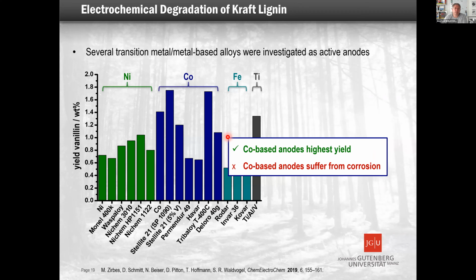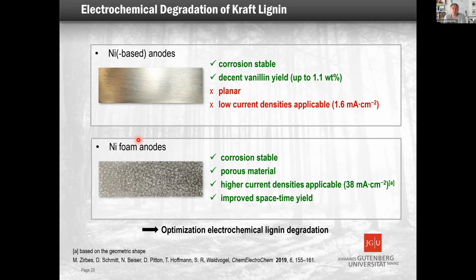It turned out if you have different metal-based anodes, which form these oxide hydroxide systems, the cobalt systems outperform all the other ones. But unfortunately, cobalt is not stable in these conditions, and you have some corrosion. You see no corrosion with the nickel systems, and therefore you more or less stay with the nickel system, which is maybe not the best at the very beginning, but it's the way to work. How can we get a little bit more out of it? The planar anodes are corrosion stable, but unfortunately, the yield in vanillin is not too high. Therefore, we have to improve that.